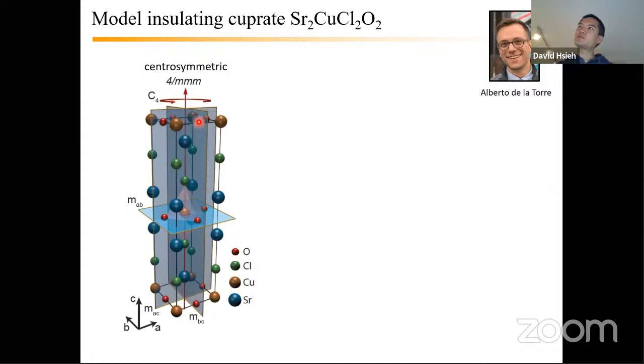We also looked at various subgroups of the point group that we used, which was 2' over M. I should have mentioned that was the C1 point group we used for our data. I don't remember exactly if we looked at the chiral ones, but I would suspect that for the data that we acquired, there's a large enough number of tensor free parameters that it would probably fit, and we'd have to take more extensive data, maybe even on different surfaces, to narrow down even further. So just based on data we have now, I would guess that lower symmetry chiral groups would fit, but we wouldn't be able to definitively say one versus another.